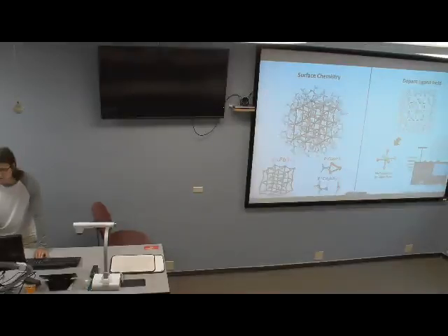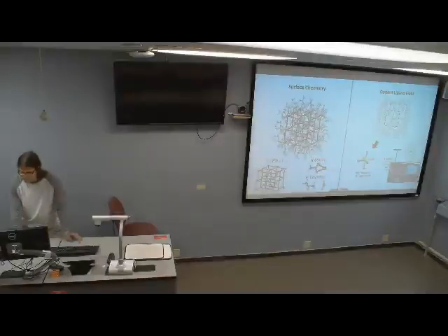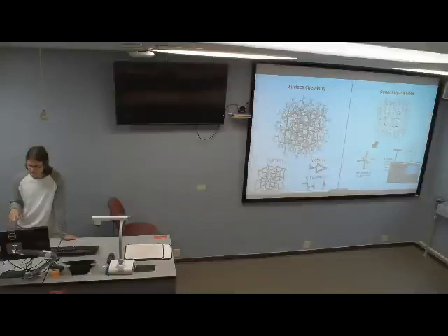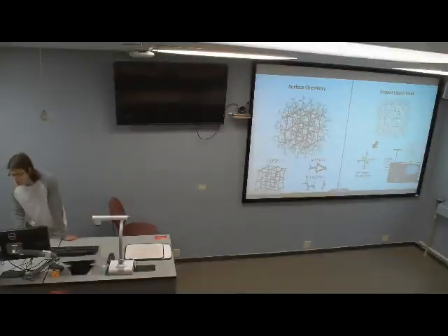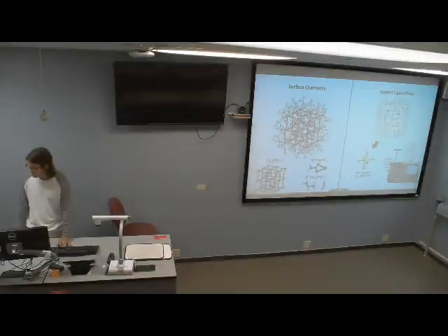mostly octahedral field. And what we were trying to model was, in experiment they found that if they doped these quantum dots with the transition metals, they were getting d-d signatures, or signatures of d-d transitions. So like a broad emission peak around 600 nanometers. And usually that's attributed to d-d optical transitions. And then we were trying to model that as well. And then I was going to show some interesting features that we saw from that model.